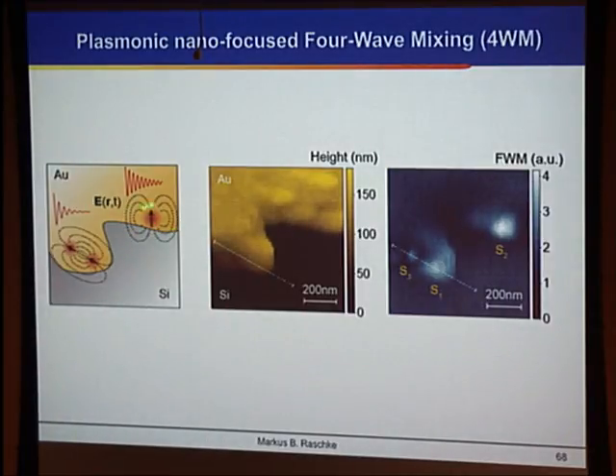So if you drive a coherent plasmon excitation in the form of a collective charge density oscillation in localized regions of the sample, we can excite one here, we can excite one here. There's a small one actually behind. So you see from the corresponding signal the localization of this emission. So these are localized surface plasmons, which are coupled both through space behind the continuous film, but also through space through some amount of dipole-dipole interaction. They may have different frequencies. And then also we have radiative emission of these emitters. And so we want to watch the emission of these, or the coupled dynamics of these three surface plasmons in space and time.